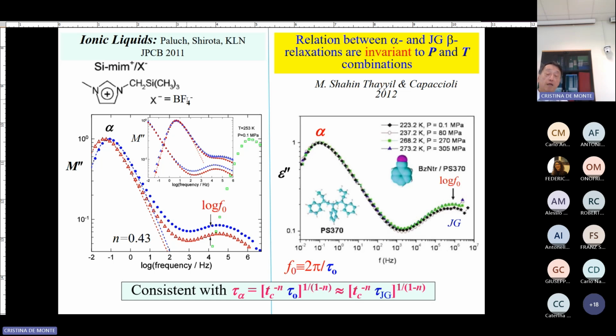So this conductivity, again, this conductivity is also simple motion. The simple motion before the ions are correlated together and move together, and that we can also call the alpha, and the so-called analog of the JG relaxation, which is ionic now. So you do that experiment and you see the so-called primary conductive relaxation peak. This is experimental, also done by dielectric. This is M double prime. This is no longer epsilon double prime. This is the electric modulus to represent ionic. And you see the secondary relaxation.